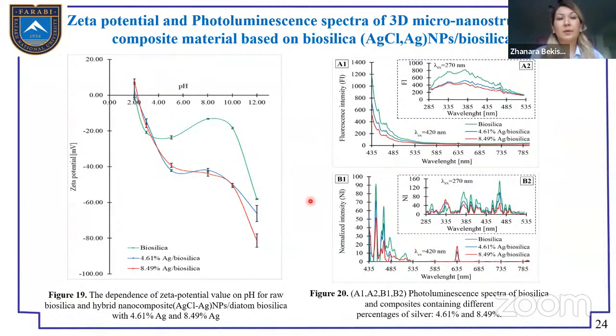The zeta potential depending on the pH of natural biosilica and the composite, and the photoluminescence, and here we can see the peaks that show particles up to 10 nanometers and particles from 22 to 25 nanometers.